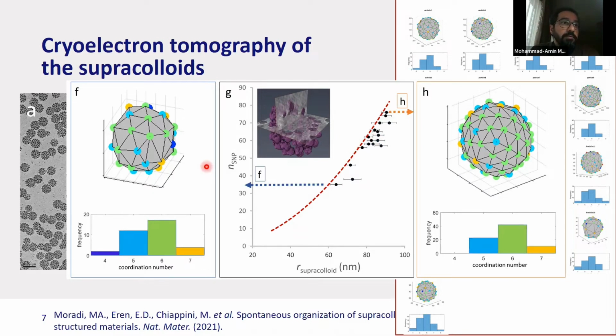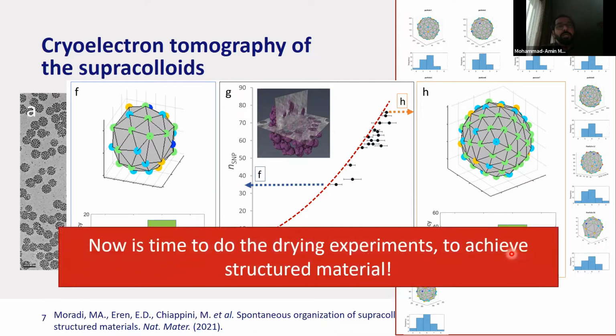So we could analyze them. We could see the structure of the silica particles on the surface, and actually this hexagonal or 6 nearest neighbors for the majority of the particles sort of confirms that we are almost fully covered with silica particles. So once we made our building blocks, the next step for us was to actually go for the drying and finding out whether we can make the 3D structure material or not.